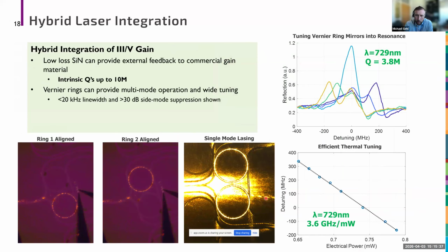In addition to directly bonding the III-V material to our photonic chips, we've also done work with more of a hybrid integration approach where we edge couple the laser gain material to our PIC. And this is an example here showing a 729 nanometer wavelength laser using our very low loss silicon nitride, with which we're able to achieve high Q ring resonators with quality factors on the order of 10 million. And we can then use that as feedback to the gain material to stabilize it and either tune the wavelength or reduce the laser line width.